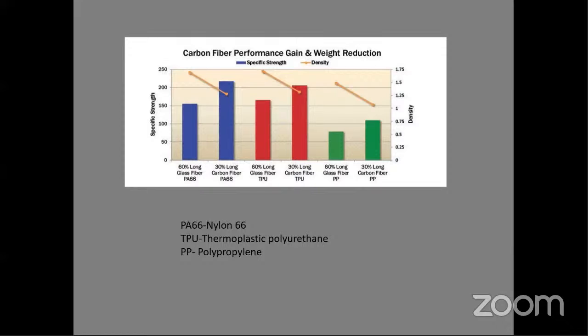So some characteristics, like when you prepare any type of composites, it depends, like when you are using different materials, percentages also change and materials also change. You can see in the picture, like the carbon fibers and the glass fibers. This is one taken from one journal. So with 60% of the glass fibers, the strength is low. In the very starting, I said glass fiber strengths are low, carbon fiber strengths are high. So 30% of the carbon fibers giving more strength. If you see the strengths here, it is almost 150, it is almost more than 200. So 30% giving more when compared to 60% glass fibers.